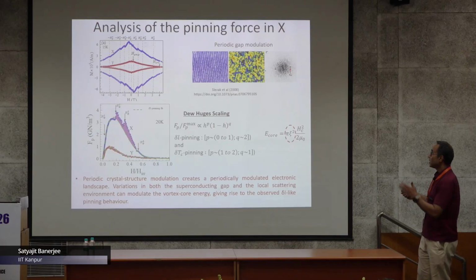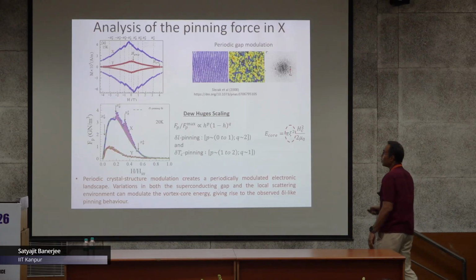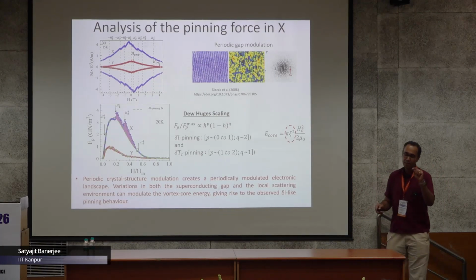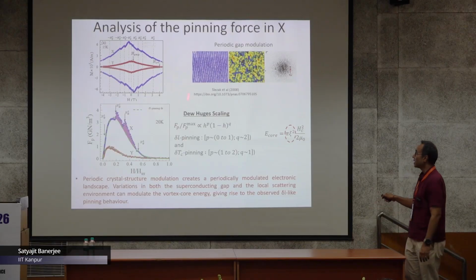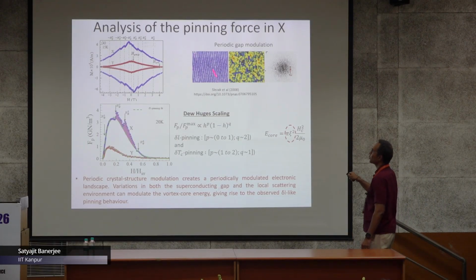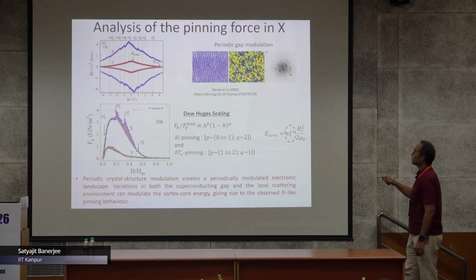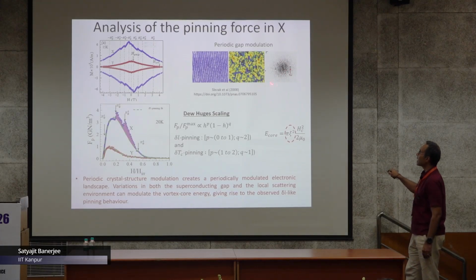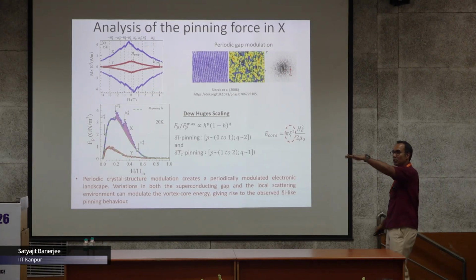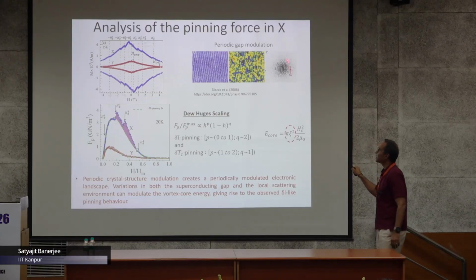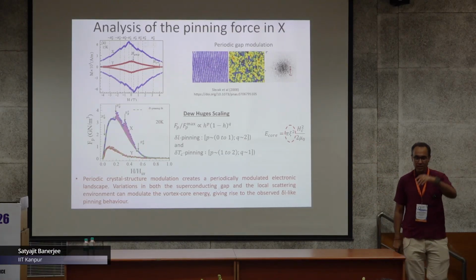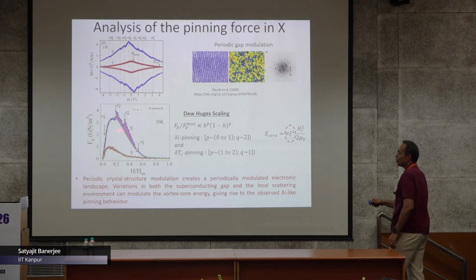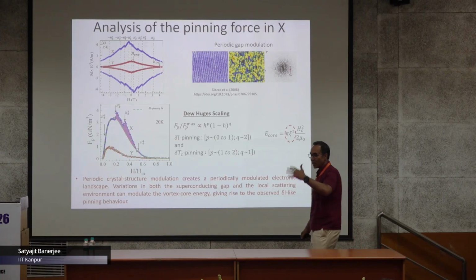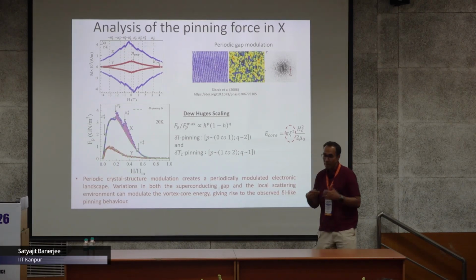People in the past, in BI2212, using STM have looked at the gap, and the superconducting gap also shows periodic modulations, where the period of the superconducting gap occurs at the same Q as the crystalline structure modulations I showed you earlier. So not only is the electronic mean free path modulating, but also the gap is modulating.